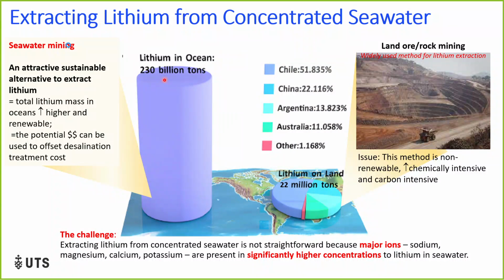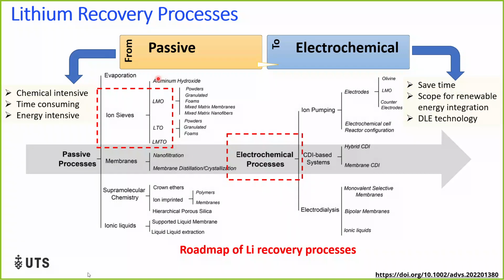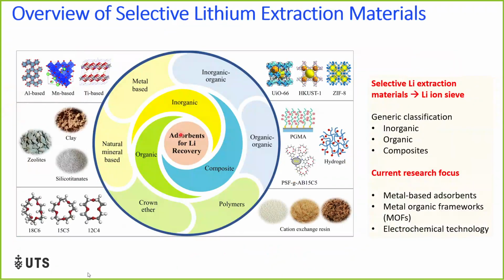So what is the challenge? Extracting lithium from concentrated seawater is not straightforward because major ions, sodium, magnesium, calcium, and potassium, are present at significantly higher concentrations than lithium in seawater. So how can we selectively collect this lithium? We investigated some technologies. Lithium manganese oxide, titanium oxide, and manganese titanium oxide ion sieving methods are among the commercial technologies. And then electrochemical processes such as MCDI or hybrid CDI can be utilized. We would like to combine these two technologies to effectively collect our lithium compound.